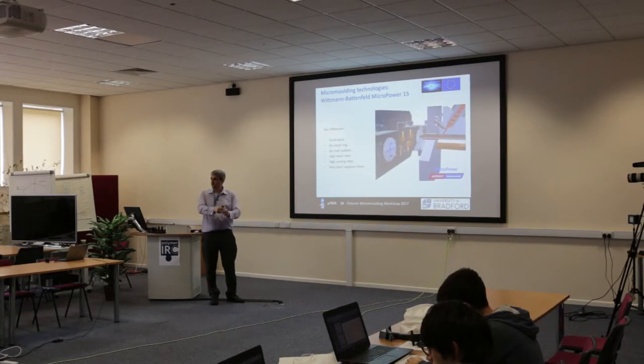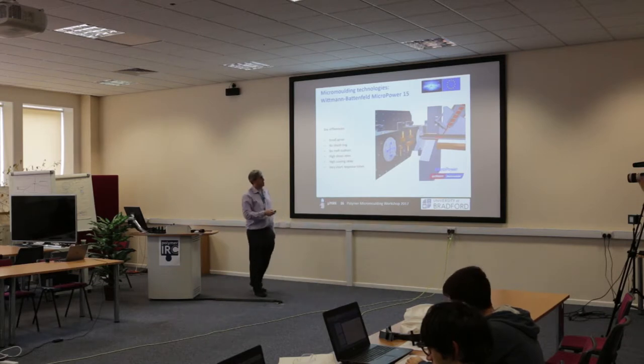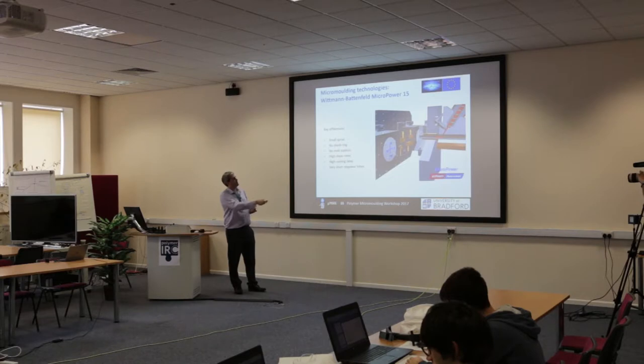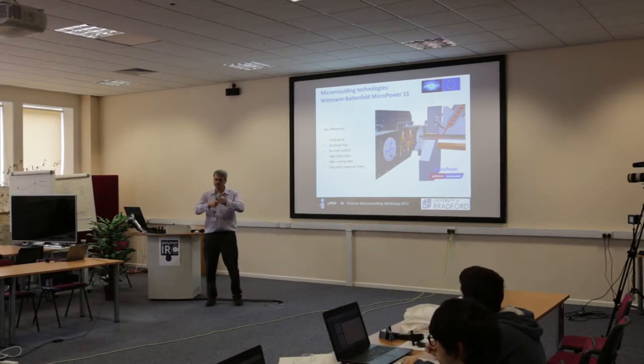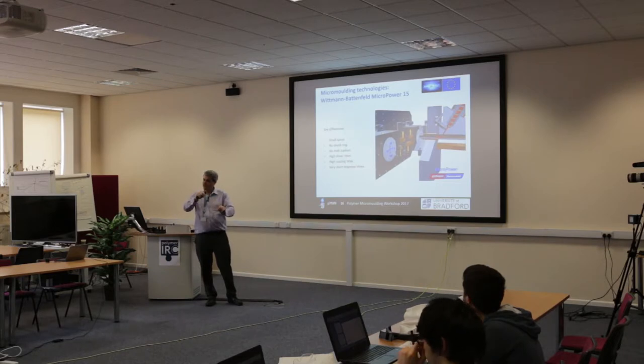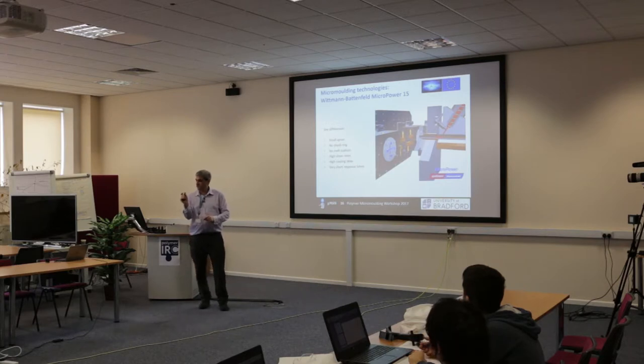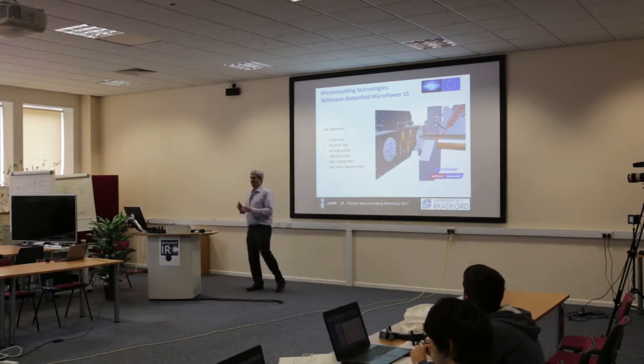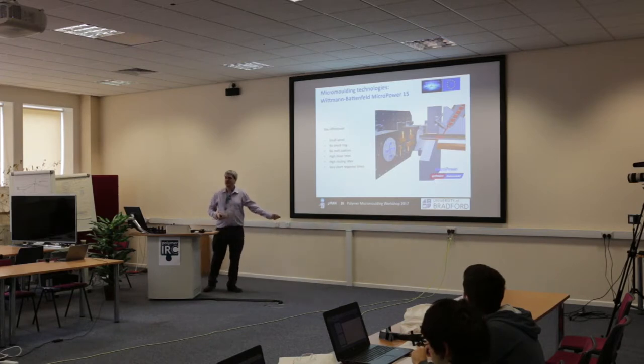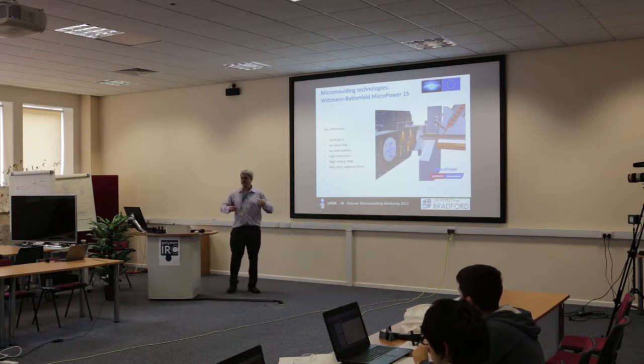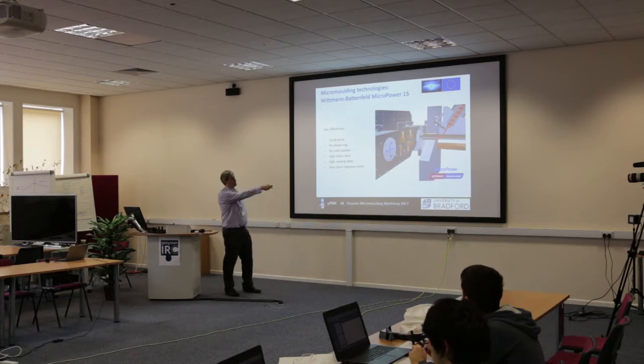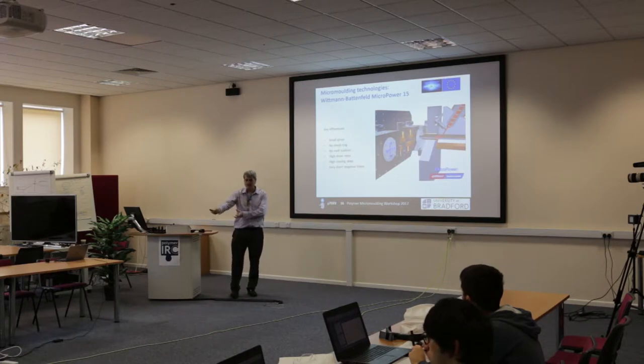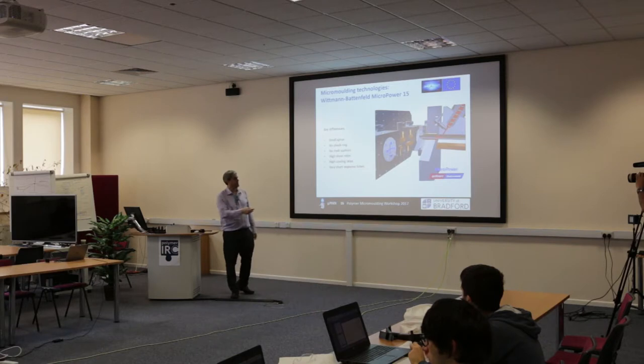In many cases we're filling the cavity in a single millisecond, so this piston must switch over incredibly quickly from filling to hold pressure. The benefits are good: all material goes into the cavity with no melt cushion left over from the shot, unlike conventional injection molding. We also get a nice separation between the cold mold and the hot material preparation area. In conventional machines, constant contact between the hot nozzle and cold mold means the first part of each shot can be slightly cooler. Additionally, because micro parts cool in fractions of a second, we can mount two tools on the same machine, reducing cycle time by roughly half.